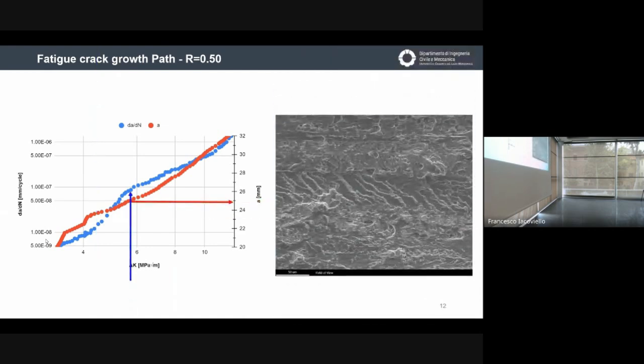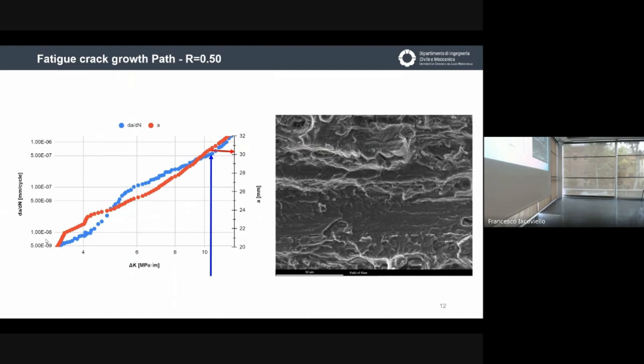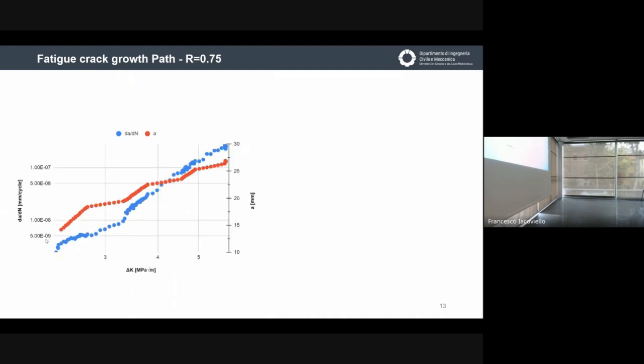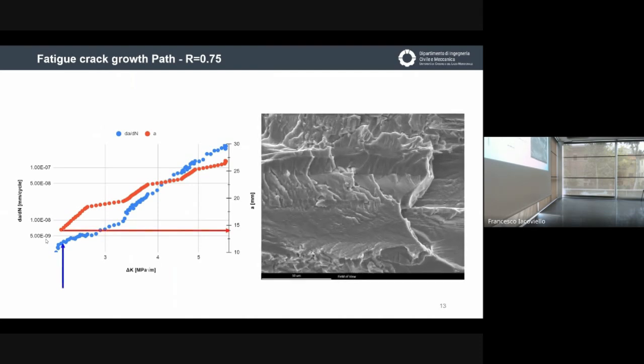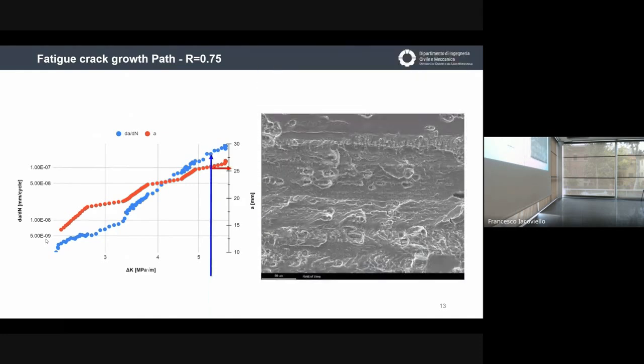And then the situation at the end of the second one is similar, with a difference. Here there is an alpha phase characterized by a sort of stair fracture. It means that the fracture is not only along the main direction of the fracture, but we are initiating a sort of secondary crack. Secondary cracks are much more evident here. For high values of delta K, you can see that at the boundary between the first and second phase, we have a sort of delamination. And so on. In the second one, the presence of secondary cracks is not so rare.